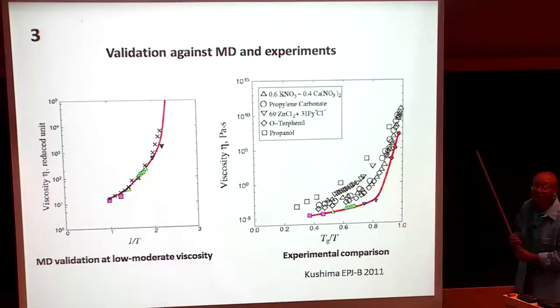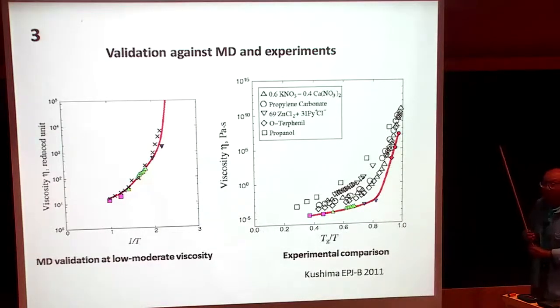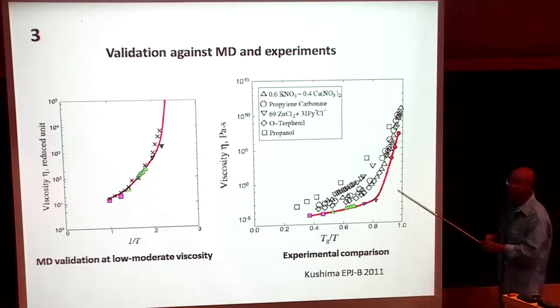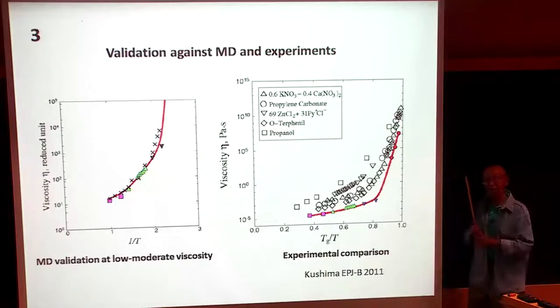But now keep in mind that we have not used anything from the experiment other than the general concept that there is this inherent structure, other than the fact that there is going to be a transition state pathway that you have to sample, other than the fact that we can use linear response here. We've not used anything else. That means an output of this is we can actually predict, first of all, TG. We don't have to take TG from the experiment.